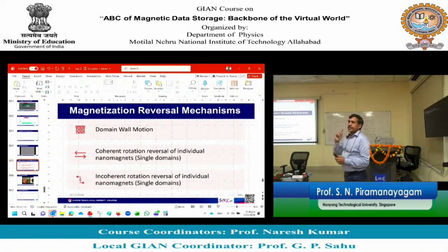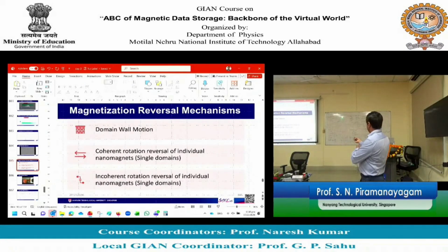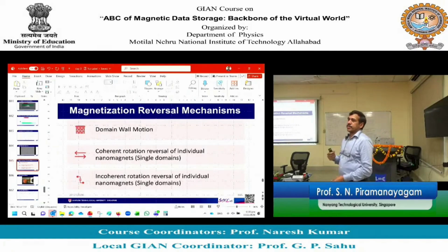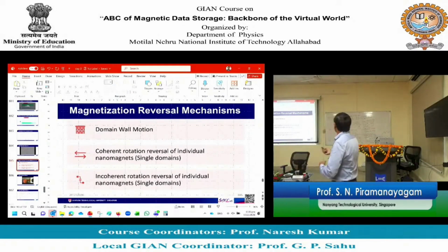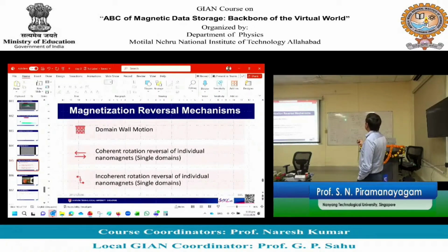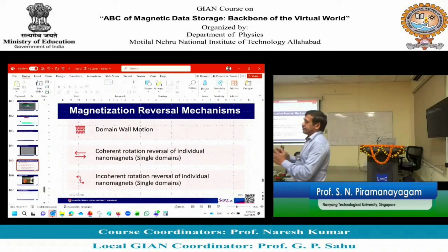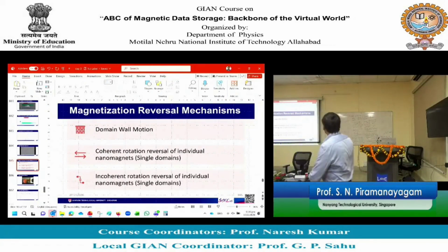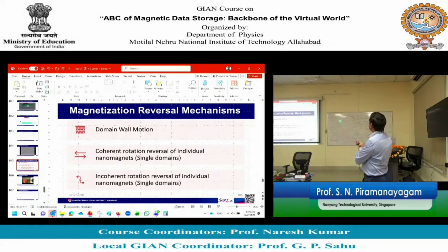Then electron spin also is like a tiny magnet, so we can say that is one reason for magnetic properties. But that is not fully true. All the atoms have electrons, all the electrons have spin. So, spin alone is not responsible for magnetic properties, it is the uncompensated spin. So, how many spins are matched or unmatched. I gave you the example of iron.